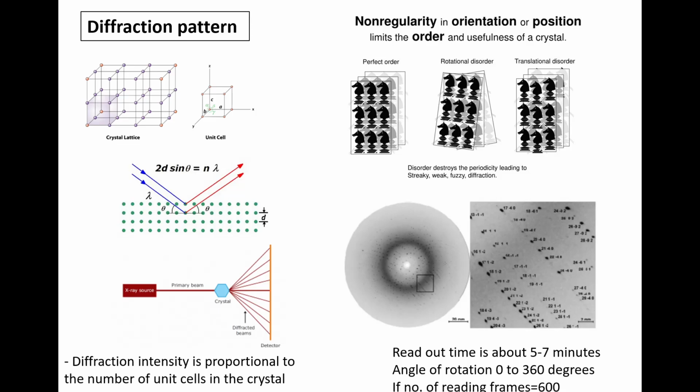So what you do is first check whether your crystal is good or fit for a better resolution image or not. You have some in-house source, you take that crystal and take an initial diffraction pattern. Look into whether you are getting distinct spots or not. If you are getting fuzzy patterns, then you have some problem with your crystal.